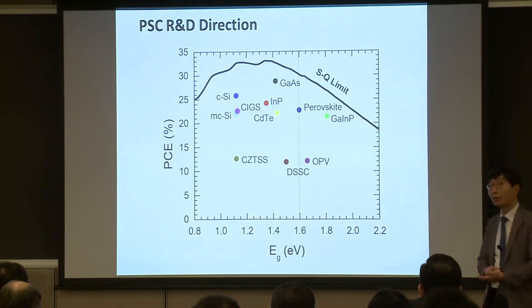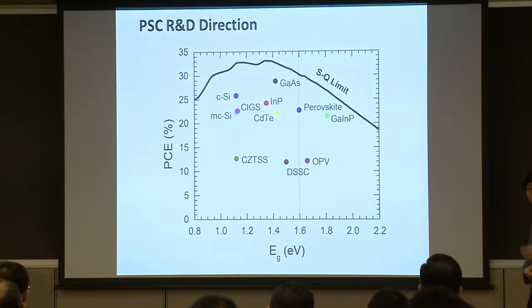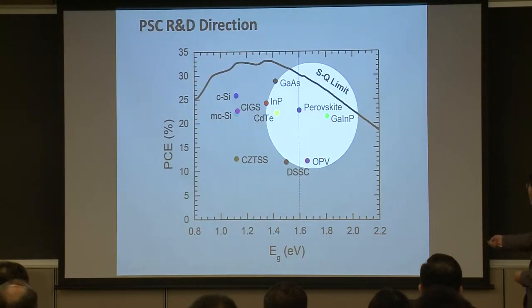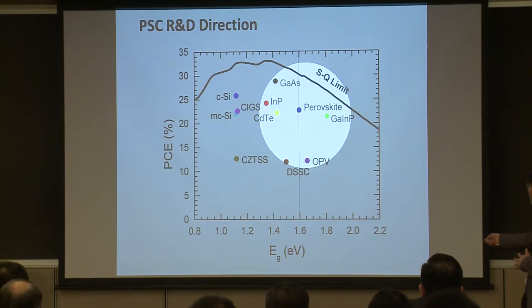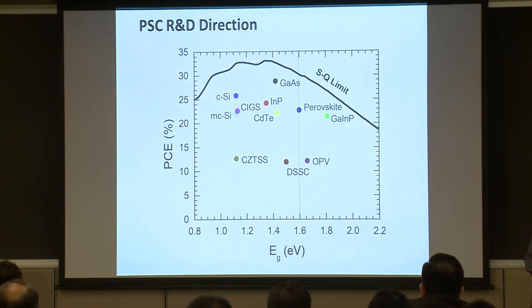The gallium arsenide already achieved more than 29% efficiency from single junction. So pretty much it is close to the Shockley-Queisser equation limit. The perovskite is now the state of the art. I take the data from the 22.7% efficiency, but still lower than the SQ limit.